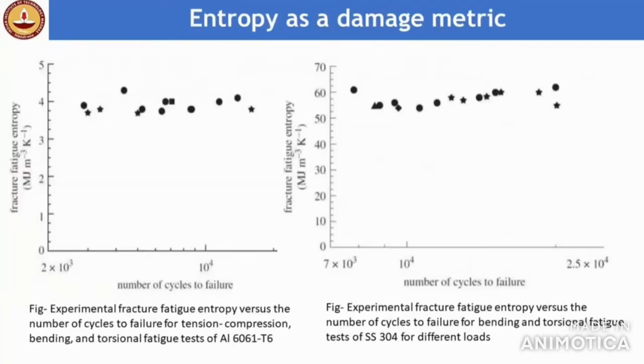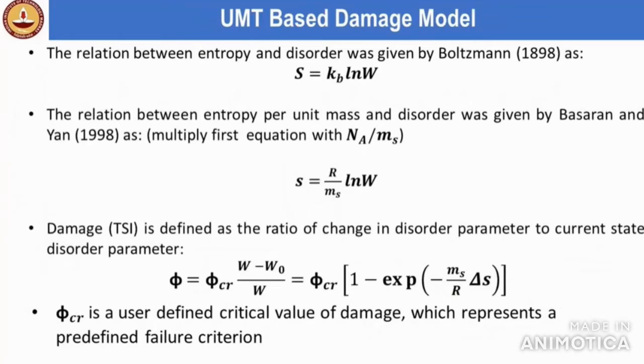So in 1998, Professor Basaran and Yan developed unified mechanics theory, which uses entropy as a damage metric. In this figure, we can see that at failure, the ultimate entropy is constant. So entropy is considered as a damage measure. In the unified mechanics theory, entropy can be calculated from the Boltzmann equation as shown here. The damage, or as we call it, the thermodynamic state index, denoted by phi, can be calculated as shown in this equation, where phi is equal to the thermodynamic state index. Phi CR is a user-defined critical value of damage which represents a predefined failure criterion.